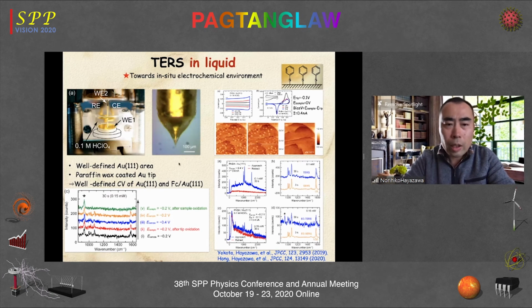But the essence is to use the paraffin wax-coated gold tip. In order to avoid the Faraday current from the taper of the tip, we coated the gold tip by paraffin to suppress the Faraday current aside from the tip apex. By using this system, we can carry out the conventional electrochemistry such as cyclic voltammetry, and also the potential-dependent tip-enhanced Raman characterization during the electrochemical reaction is now possible. And of course, this work can be used for the biological samples in liquid environment.